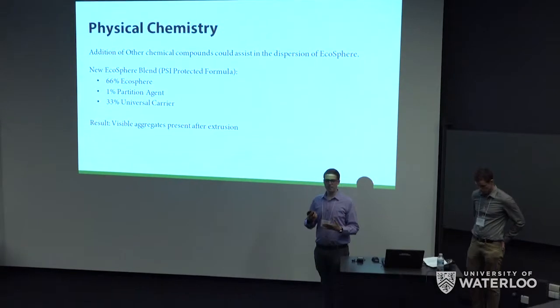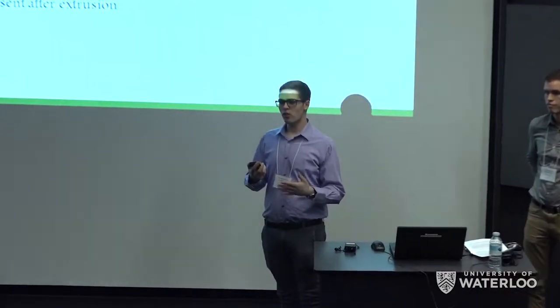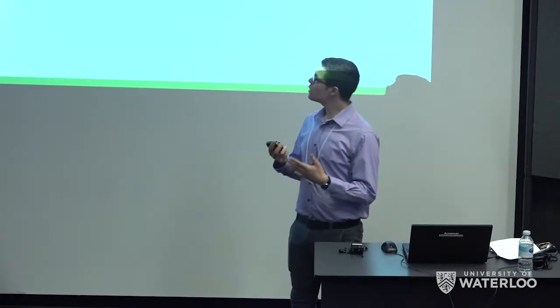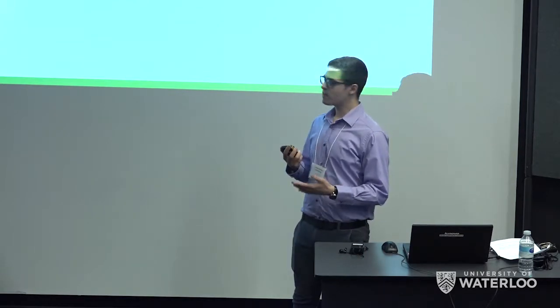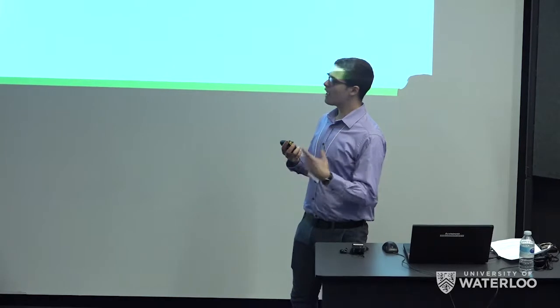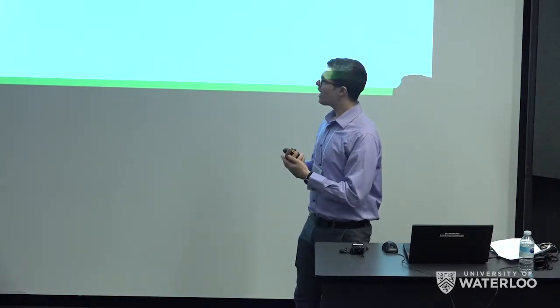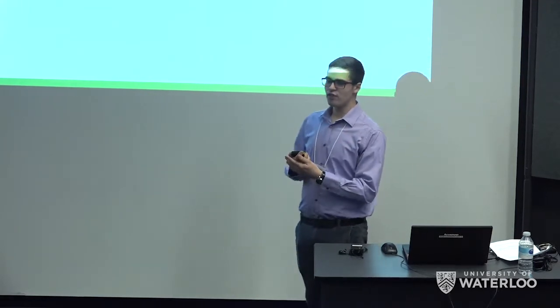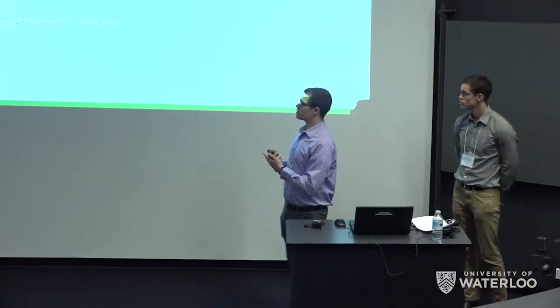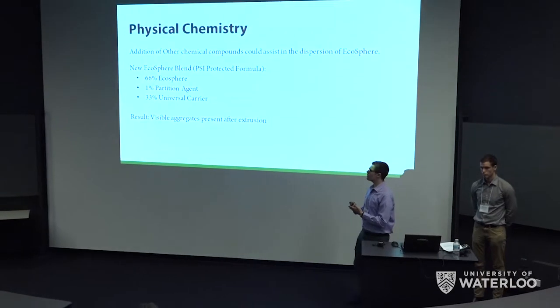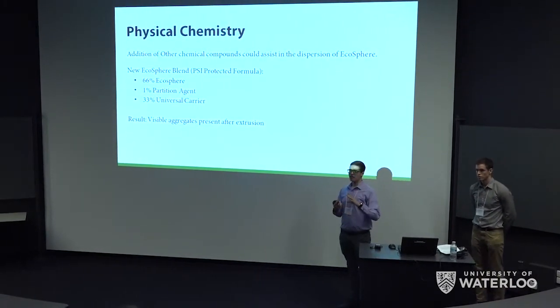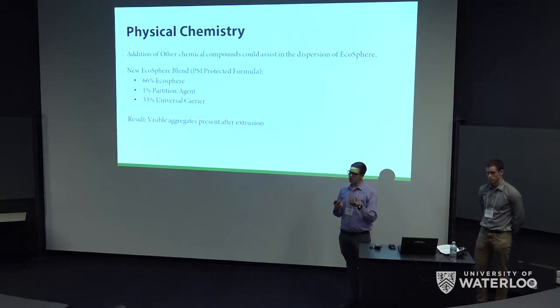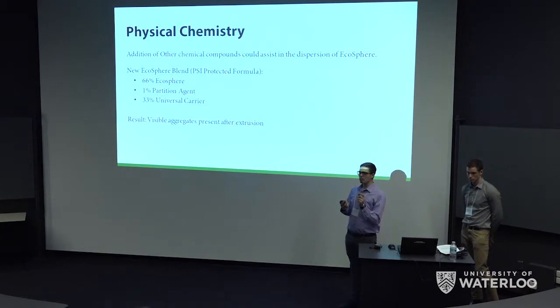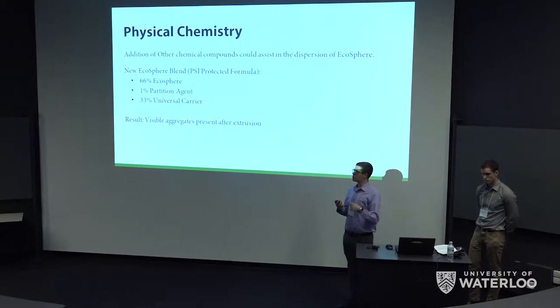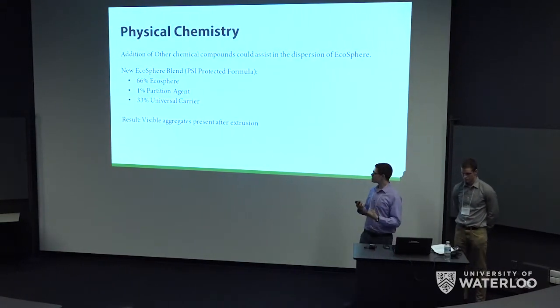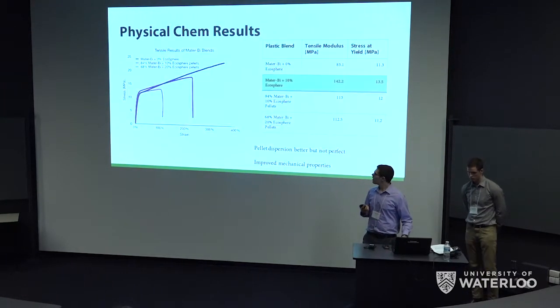increasing or adding new additives to the material blend in order to increase the shear or reduce the amount of shear that is required in order to break up the aggregates. So we worked with one of the companies that helped us blow our film called Polymer Specialties International, and they're based out of Newmarket. And they are developing a proprietary blend that uses Ecosphere. And they also incorporate a 1% partition agent and a 33% universal carrier. And what the universal carrier does in this blend is just allow the partition agent to be compatible with the Ecosphere. The important thing here is that the partition agent has a shape that looks kind of triangular, and so the purpose is, on a micro scale, to be able to break up those nanoparticle aggregates while they are being extruded. However, we noticed that after we did this, there were still visible aggregates present, even though anecdotally they were a little bit less.